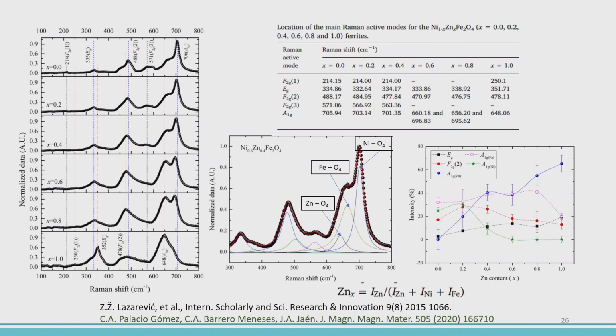Other method, you see, there are 2 methods now that I have told, 2 with X-ray and now with Raman. With Raman it is also possible to do that when we concentrate on this band here. And here we show a fitting showing the 3 components fitted with Lorentzians. And from this formula here, determining the intensities or the area, we can determine the zinc content at the tetrahedral site.